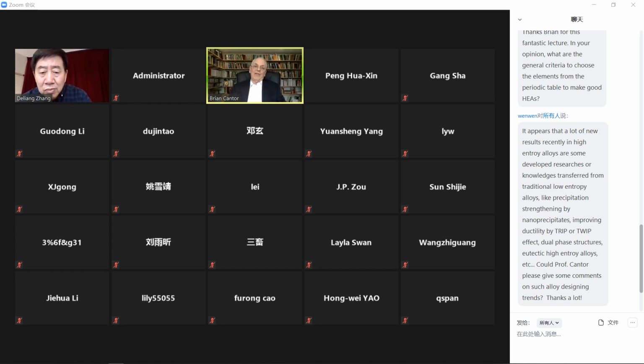You go and try and do a thermodynamic calculation on a thermodynamic database for a 7-component or 8-component system, and you'll find that a lot of the data is missing. Of course it's missing. We've never made those alloys before. Thermodynamic calculations only work when you're within the range where you already have some data, quite a lot of data to be successful, to be honest. So our thermodynamic understanding is all based on existing materials. The experimental data, and the theories, are usually based on dilute solution approximations. So our thermodynamic calculations help us, but they don't help us to extrapolate into the middle of multi-component phase space very much. They're an aid, and it's helpful to use them.